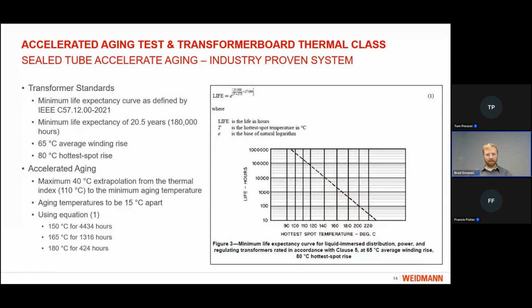Looking back at the transformer standards that Tom mentioned previously, the C57.91 brings this life equation or life expectancy curve shown on the right. The minimum life expectancy is defined in the standard as 20.5 years or 180,000 hours. And this again is the 65 degree average winding rise, 80 degree hot spot.